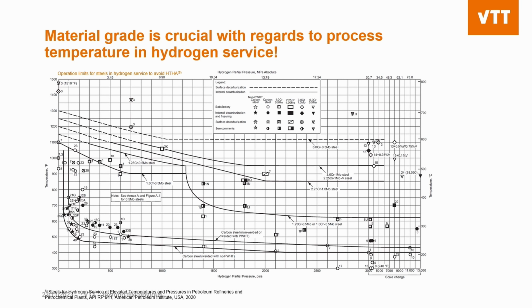Material grade is considered to be very important with regards to process temperature in the hydrogen service. The graph here shows operation limits for different steels in hydrogen service. This work is mainly achievement by G.A. Nelson, so these curves are often referred to as Nelson curves. In the graph, the x-axis stands for hydrogen partial pressure and y-axis stands for temperature. Now, if we look at a single curve here, below the particular curve, the combination of temperature and hydrogen pressure form a safe area against high temperature hydrogen attack for that particular material. And above the curve, there is a danger for high temperature hydrogen attack.